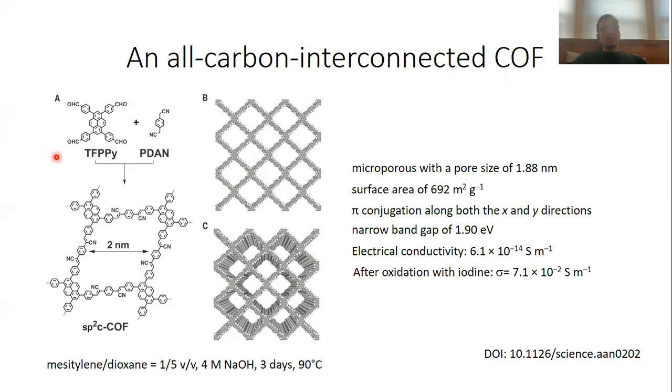One such reaction is the so-called Knoevenagel condensation reaction, also a reaction that has been known for a long time in organic chemistry, but it has just recently been discovered for making extended solids. So essentially here you react an aldehyde, in this case a tetratopic aldehyde, which is planar, a square planar building unit,